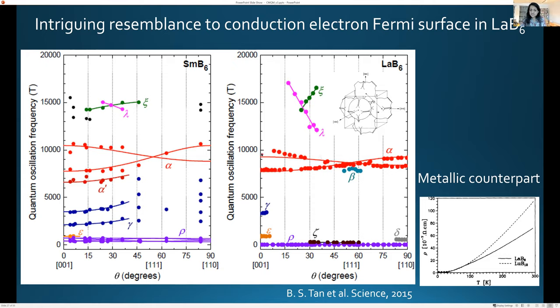And really interestingly, they have a similar frequency and a similar angular dependence to what we see in the samarium hexaboride, which seems to imply that somehow the Fermi surface of the samarium hexaboride seems to be in some way remembering the conduction electron Fermi surface it had before it got hybridized.